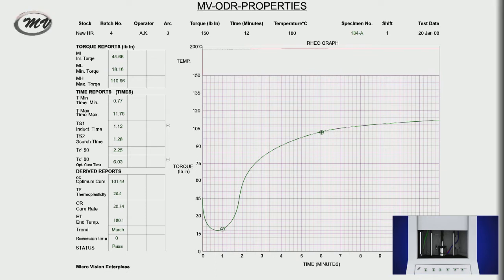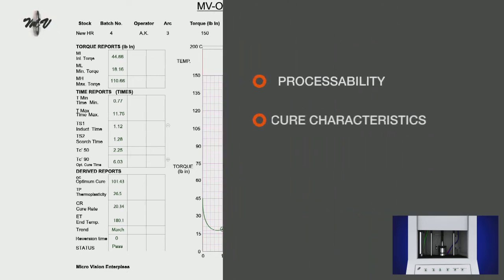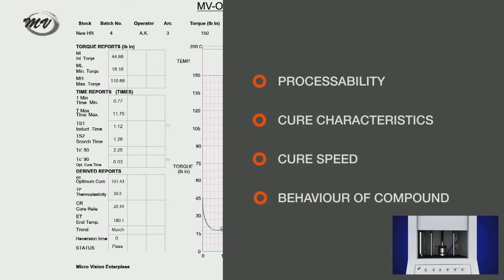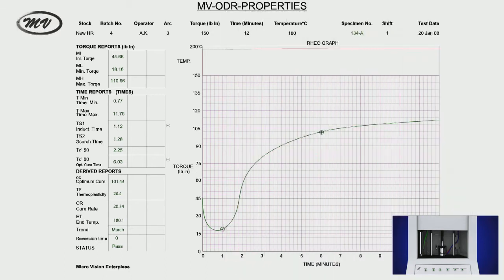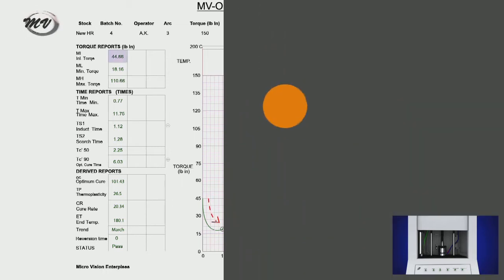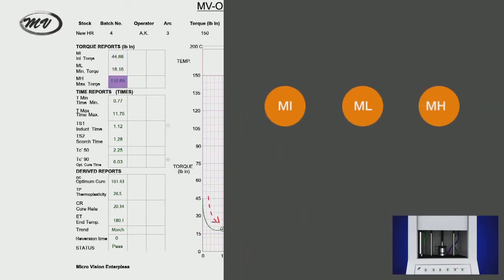The acquired data gives exact information about processability, cure characteristics, cure speed, and behavior of the compound after vulcanization. An expert could easily monitor the initial trough, that is, the processing behavior of the compound, the slope of rise during the cure phase, and the final shape of the curve according to internationally designated parameters like MI, ML, MH, TS2,